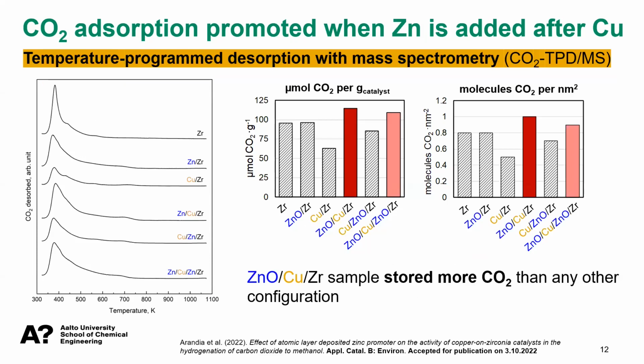Another important characteristic, you can imagine that if we are doing CO2 hydrogenation, it's very important the amount of CO2 that we can have adsorbed on the surface. So if we have more CO2, most likely we can convert more CO2 to methanol. So this is an important parameter. And we evaluated this CO2 adsorption capacity by temperature program desorption with mass spectrometry, so CO2 TPD analysis.